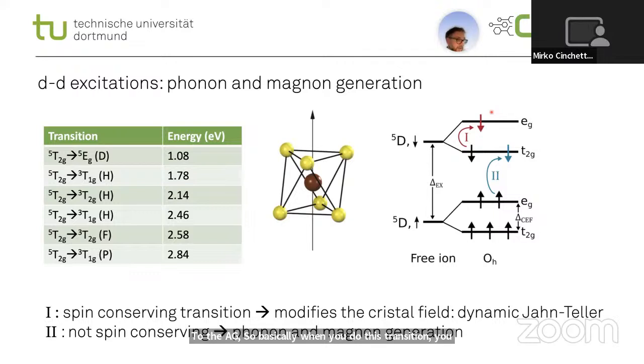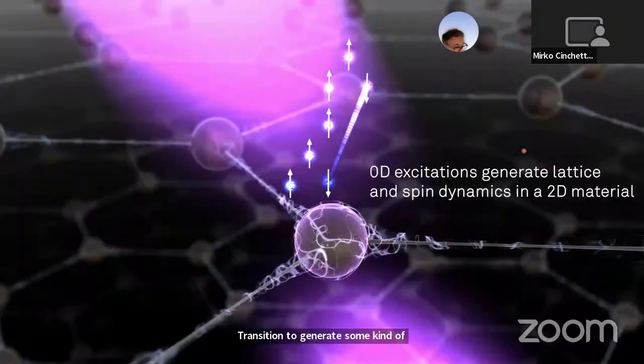And this will generate a Jahn-Teller distortion of the ligands. And we can expect that this will lead somehow to the generation of some kind of phonon modes in our crystal. The second transition goes from 5 to 3. This means that you are also flipping a spin. So you're not only generating phonons in this case, but presumably you can also use this transition to generate some kind of spin dynamics, for example, magnons.